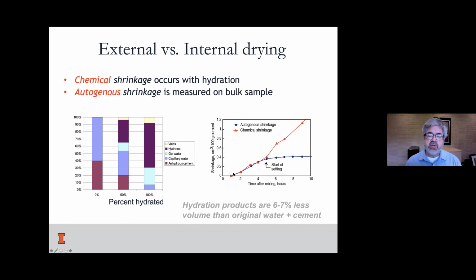So if we were able to measure this with time, we would see autogenous shrinkage and chemical shrinkage. Autogenous is on the bulk sample. Chemical is just the definition of the materials themselves. And chemical shrinkage in red just goes up with hydration, keeps going up and up. And then at some point, there's a departure. They basically are the same thing when the concrete is fresh and fluid. If there was any reduction of volume, the material just collapses on itself. And so here they are the same. Start of set, there's a departure.